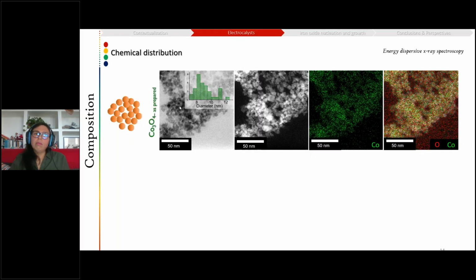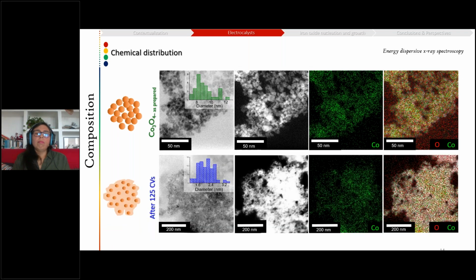Just one last time of this really nice video that I liked very much. And then, okay, so is this a real amorphous layer, or how is our material changing? So what we did was to compare our pristine material, which of course is composed uniformly of cobalt and oxygen, and then particles that we recover from the surface of our electrode. Actually, we are observing them directly on the surface of the electrode, and we see that there are very small crystallites, and there is an amorphous matrix around it.